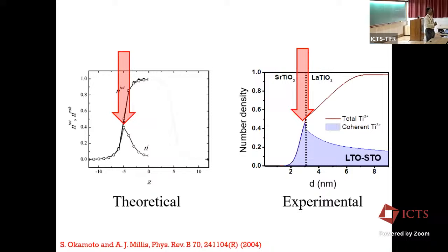You know that. It's a quantum paraelectric, simply because the dielectric constant keeps increasing as you go to low temperature. So the question was, if I increase the dielectric constant and the screening is changing very drastically, would that impact the distribution? And we found that it didn't change anything at all. So LAO-STO we looked at more than one temperature, but LTO-STO we're looking at room temperature.